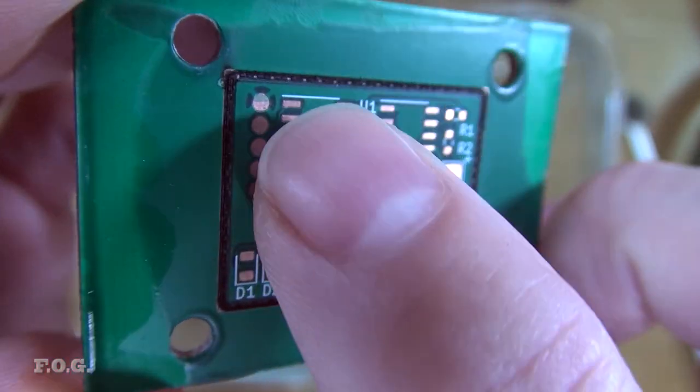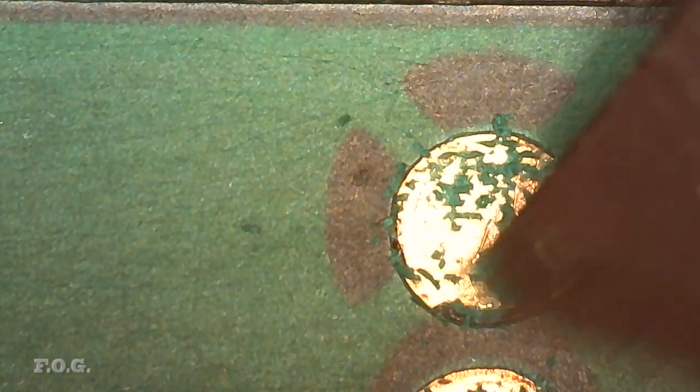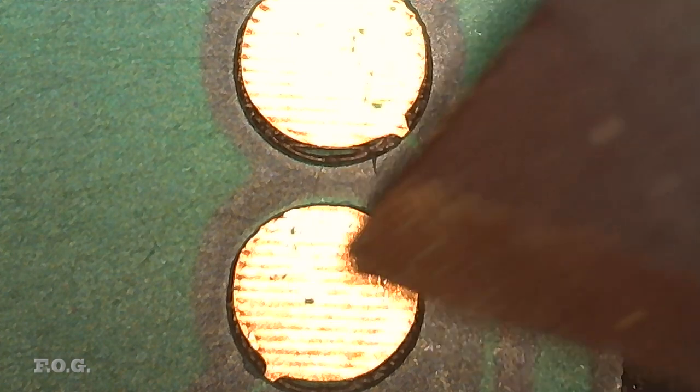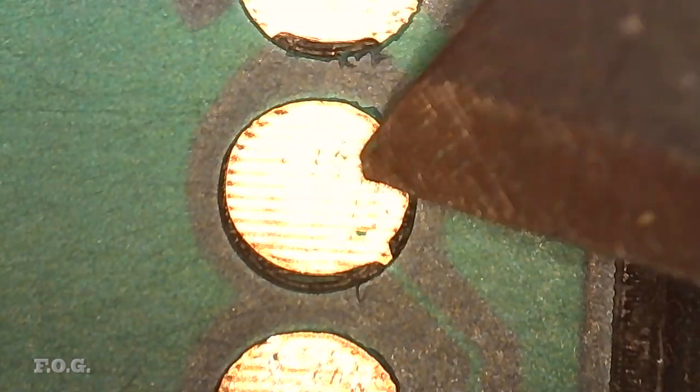Under the microscope, we can actually see that these are tiny lines of resin that have remained on the pads. The lines are of course at a 0.1mm pitch, which matches the clearing operation that I've been using, which is really easy to knock these off. So it's not a big problem in that sense. I also feel a subtle washboard effect when I'm running the cutter knife over the pad. So the laser must be eroding a tiny bit of copper when it's clearing those pads.